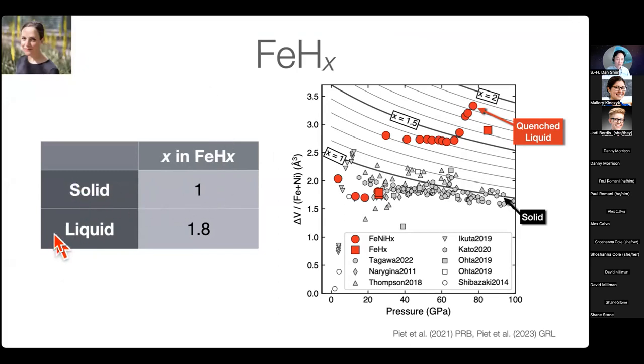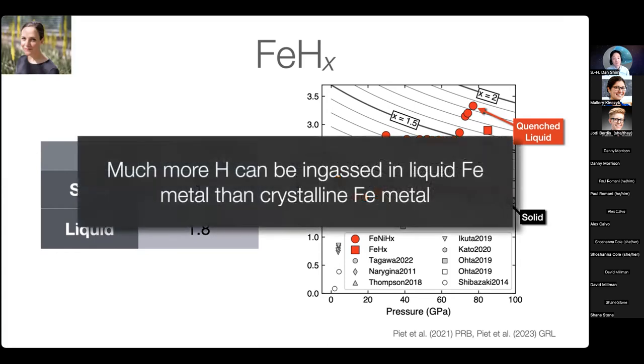Recently, we were able to melt iron in a hydrogen medium, and we found that approximately twice more hydrogen can alloy with iron when iron is in molten conditions, which means that the molten interior of the ice giants or hydrogen-rich planets may have a large capacity to store hydrogen.